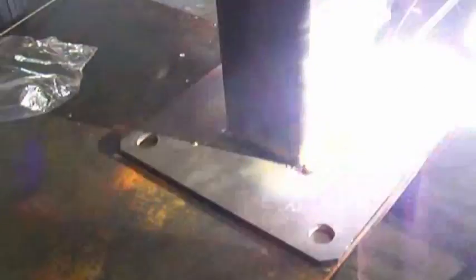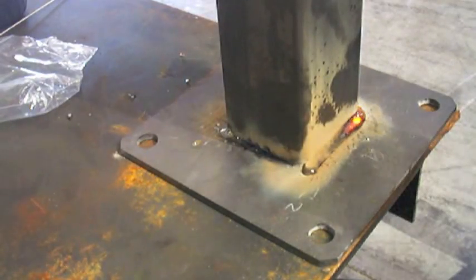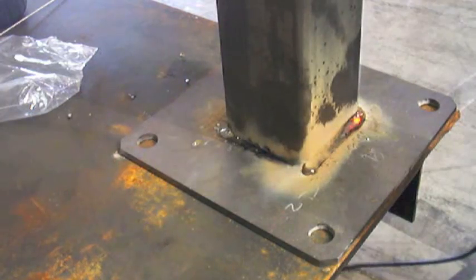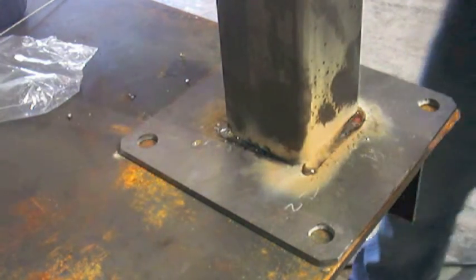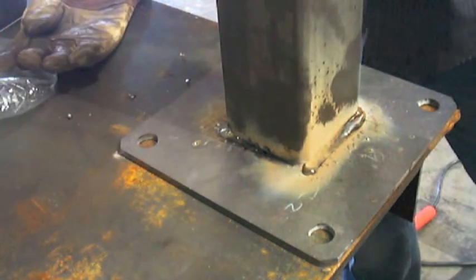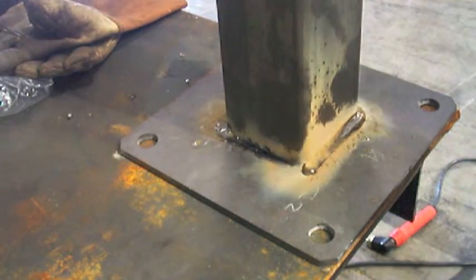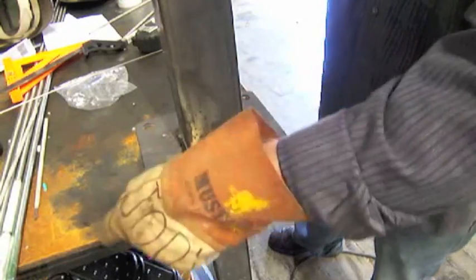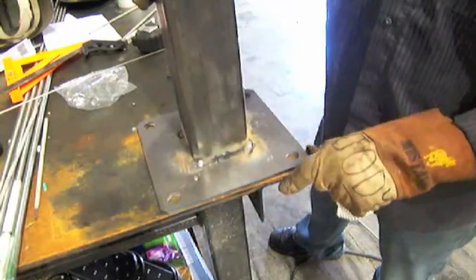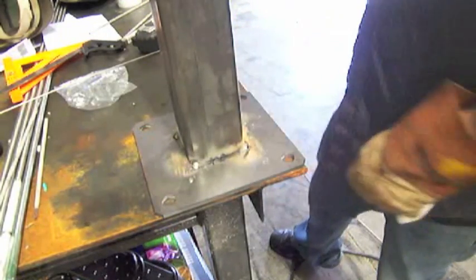Before I settled in at a good amperage, because I haven't done a whole lot of stick welding with the PowerPro 256, I was a little hot. When it's a little hot like this and I've got the arc force kind of high - these are some old 7018s that have been out in the open for years. I knew I would have a tendency to stick, so I turned the arc force up and turned it up a little hotter than normal. I still did okay, but I got a few BBs. I settled in at about 138 amps for the rest of it, which is actually a little hotter than you would normally run good 7018.